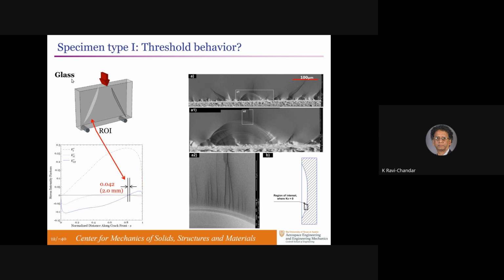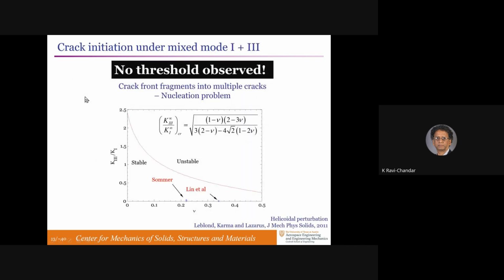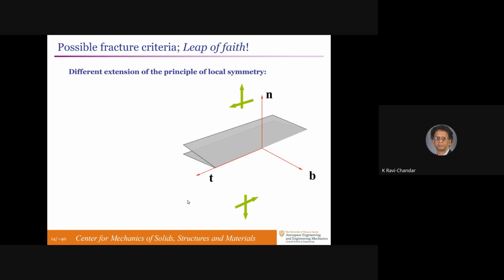This is about the most brittle material you can get. We've repeated this experiment in other materials like polymers that are slightly plastically capable in deformation, but they still do. As long as it's brittle fracture, they still do the same thing. They fragment into multiple facets the minute you do a mode 3 loading on it. So there's no threshold. This is where our results sit. As soon as you apply a small magnitude of mode 3, the crack starts to flip.